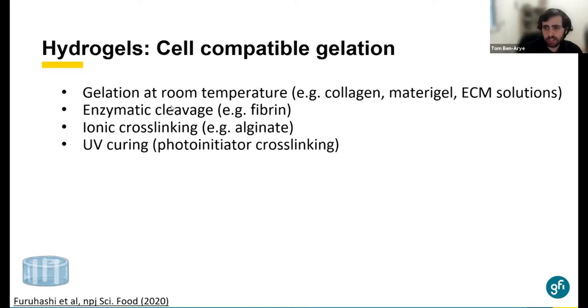Other options are enzymatic cleavage. For example, fibrin that we often use in the lab. Fibrin starts as a fibrinogen, a molecule that is a liquid that can be a part of a solution. It could be a solution in room temperature. And when we add the enzyme thrombin, the fibrinogen is cleaved, generating fibrin that cross-links into a gel. So again, fibrin is something that we might not want to use because it is kind of expensive and animal source, but we can think theoretically about enzymatic cleavage as a way to generate the gels. Another option is ionic cross-linking. As we know, alginate could be a solution that in the presence of calcium ions undergoes cross-linking. So that's another option for a cell-compatible gelation.